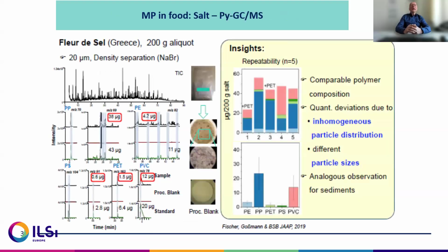The second example is microplastics in salt by pyrolysis-GC. Here is a sample of 200 grams. At the beginning, we did a density separation, because in salt there are very often a lot of very small stones, and you have to remove the stones for the analysis. And here we found in this sample 38 micrograms of polypropylene, 4 micrograms of polyethylene, and 12 micrograms of PVC, and so on, as shown on the left side.